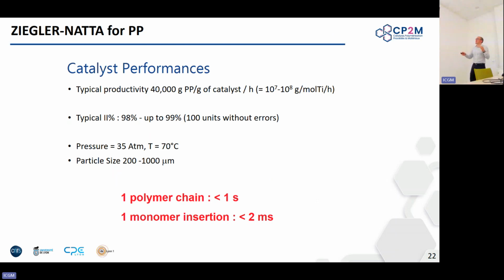A comment about catalyst performances. Ziegler-Natta polymerization tends to have one of the best productivities, especially if you take into account the fact that of the titanium that is on the solid support, that is your pre-catalyst, only a few of them really turn into polymerization active sites. So these are values that don't take into account that you are only activating maybe 5% of the titanium. But even if you take into account all the titanium that you deposited on the magnesium dichloride, you end up with values where you can produce like 40,000 grams of PP per gram of catalyst per hour.